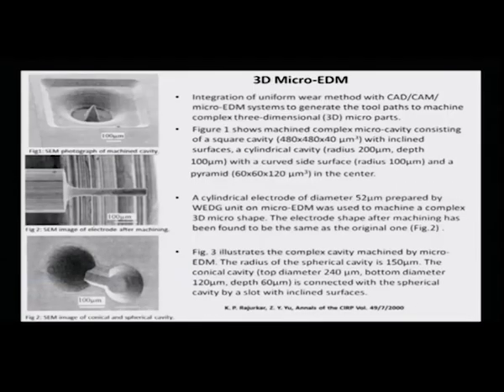So, this is one very fine example of what CNC wire cut EDM can do. Apart from that, there are many other applications of the micro EDM process. One of the examples here shows a machined complex micro cavity consisting of a square cavity, which is about 480 microns wide and 480 microns long, with a depth of about 40 microns, and there is a small pyramid at the center, and the whole machining is being made by a micro EDM operation.